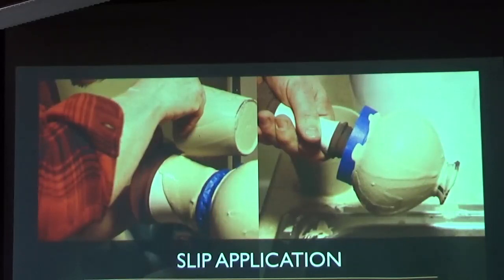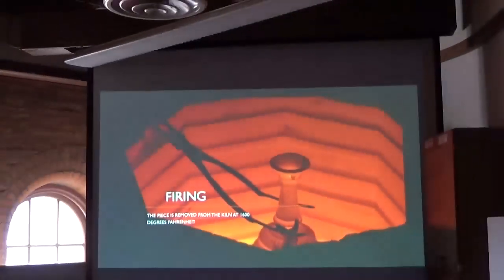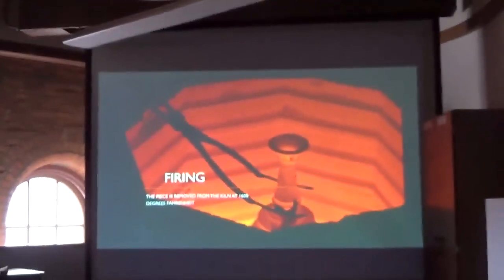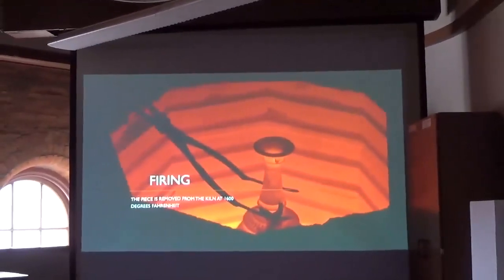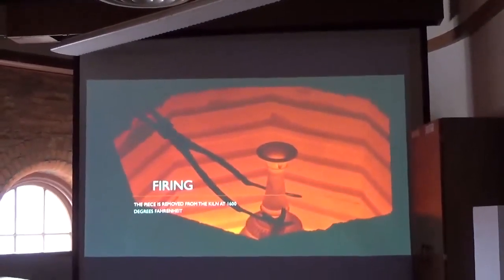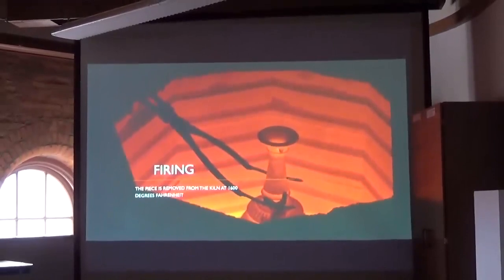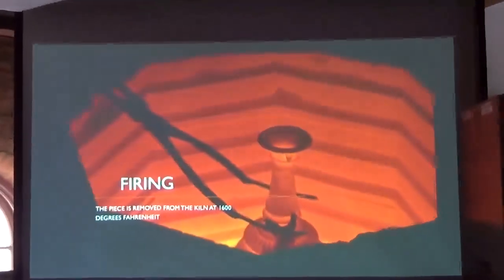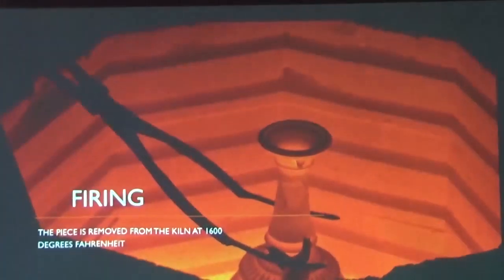So after the slip application, again, immediately, don't let it dry, it goes right into a hot kiln. And that's pulling it out. That is about 1600 degrees. I like to pull my pieces. You actually see there, those are tongs coming in, because you don't want to grab that. And I actually have a leaf stuck to that tong. And that's a half second before I actually grabbed that piece, and that leaf just immediately combusted. It is in such an environment that is so hot.